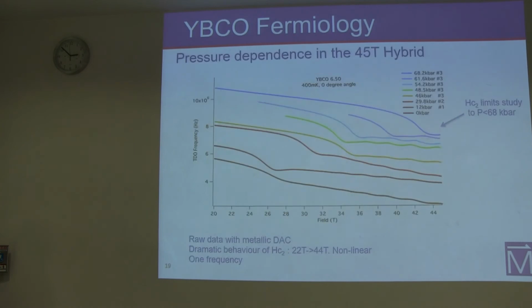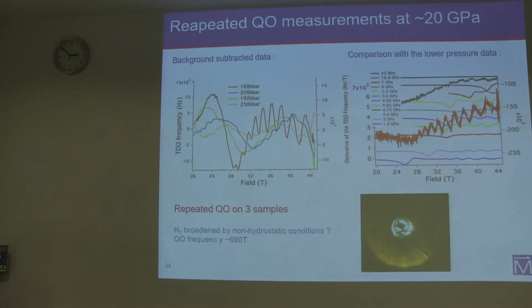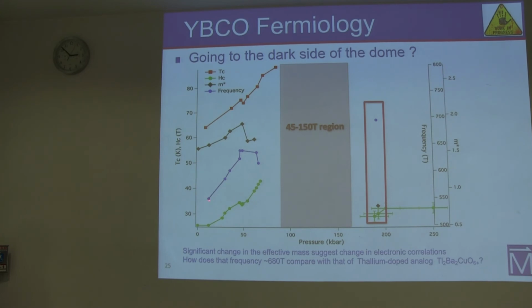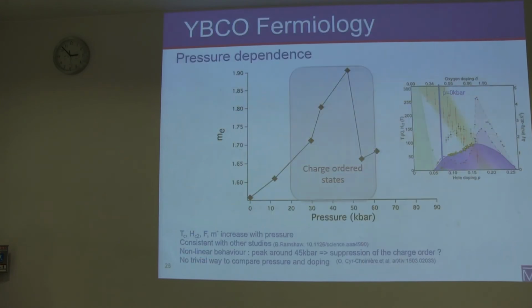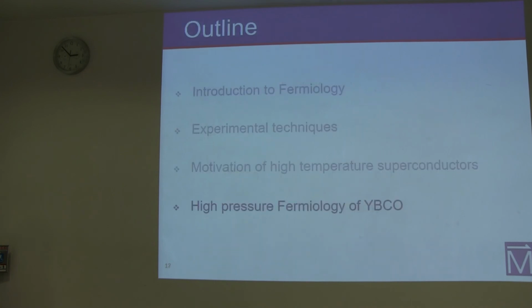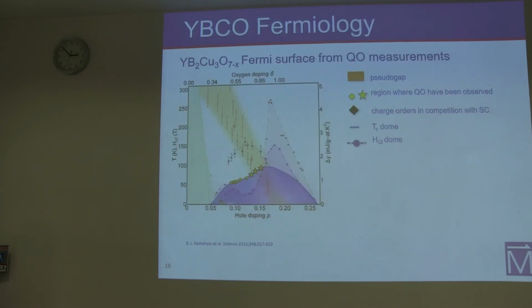And going back to our phase diagram, we start here. Where is the critical field? Here we are at 28, 29 Tesla for the critical field and 65 Kelvin for the TC. So here the TC is 65 Kelvin. If we go back to the doping plane, when you start at 65 Kelvin, the field is about there. I think here we go back to the same comparison, a factor of 2.